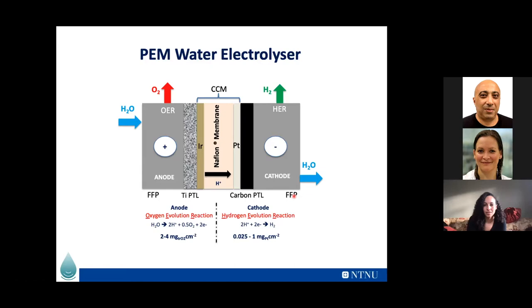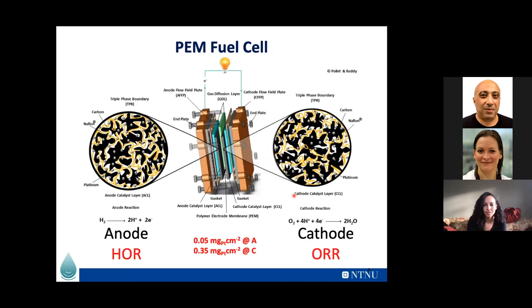Now let's talk about PEM fuel cells. They have been around for many years, some major fuel cells. We are looking at, again, the use of PGMs, platinum, as the main components on the anode and cathode side, where on the cathode side you've got the oxygen reduction reaction, and on the anode side you've got the hydrogen oxidation reaction. Again, the loading there is around 0.05 milligram per square centimeter of platinum on the anode side, and 0.35 milligram per square centimeter on the cathode side.